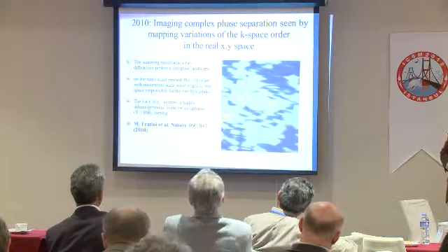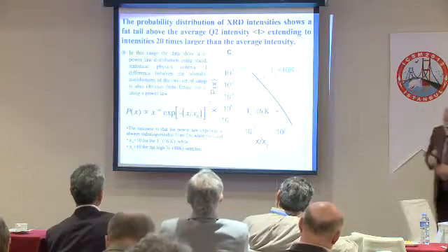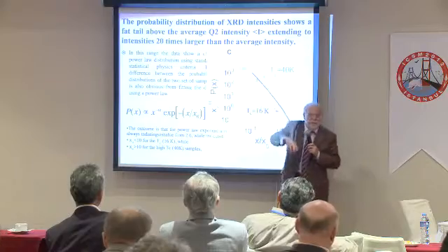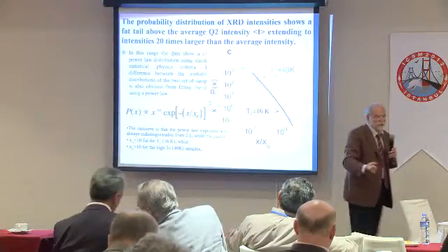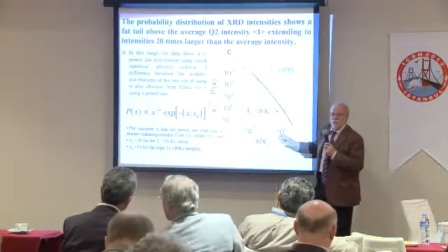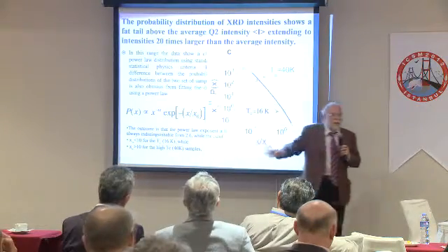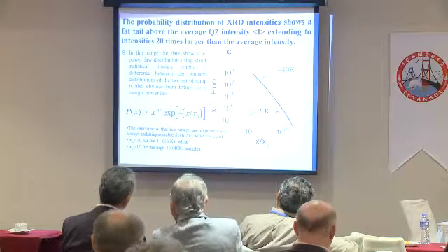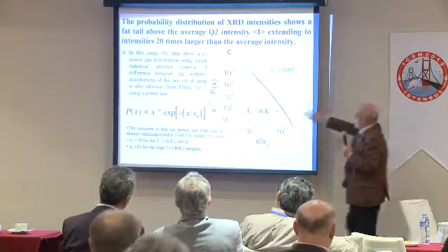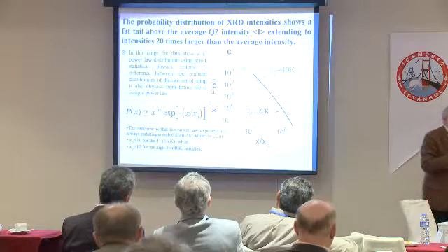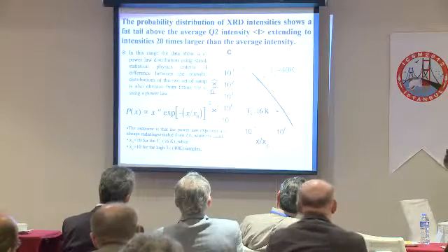So what we see now is that for this kind of patch, if you plot the intensity of the diffraction, which is the volume of the order, then the volume of the order scales with a power law distribution with a cutoff. Why a cutoff? Because infinite size of the grains is impossible, so it's fundamental that there should be a cutoff. And as you go from 40 Kelvin to 16 Kelvin, the cutoff goes down. When you go to 60 Kelvin, to reach a nearly Gaussian distribution, the cutoff is very large.